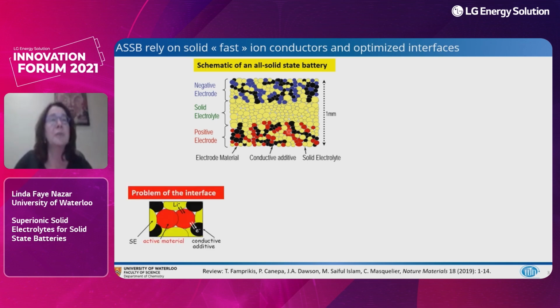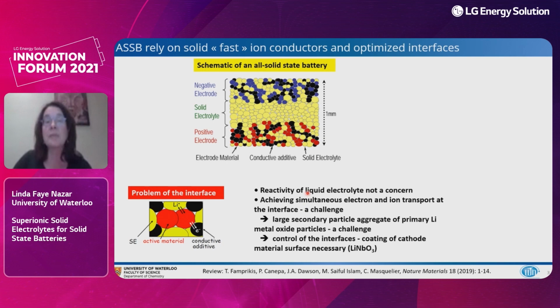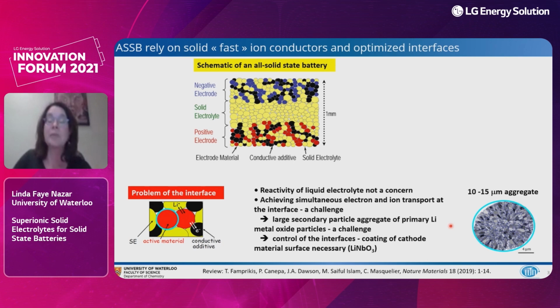So we have the problem of the interface. I'm going to focus more on the positive electrode, which is the same thing as the triple phase boundary problem in fuel cells. One has to deliver the electrons and the lithium ions to the positive electrode material effectively simultaneously. So while we don't have the problem of the reactivity of the liquid electrolyte, achieving the simultaneous electron and ion transport at the interface is a challenge. And it's particularly a challenge because many of these materials, and we're not going to talk about those beautiful single crystals that Jeff showed, but more traditional NMC type materials, are comprised of primary crystallites that are then aggregated into these fairly large secondary particles.